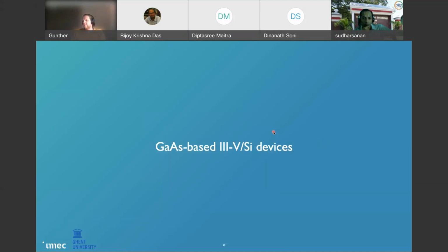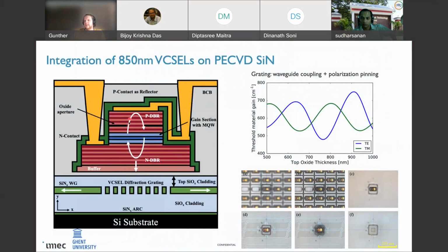So now let's have a look at gallium arsenide-based devices. I already showed you this picture of the VCSEL, so a gallium arsenide 850 nanometer VCSEL that was transfer printed on top of a silicon nitride waveguide circuit. In this case, it's PECVD silicon nitride, where we use the grating to couple light into the silicon nitride, but actually we also use it as a way to pin the polarization of the VCSEL. This is a one-dimensional grating, which will have a different reflection coefficient for TE and TM polarized light. And by optimizing that, by choosing the proper spacing between the VCSEL and the silicon nitride, we can create a substantial difference in threshold gain for TE and TM polarized light, and hence pin the polarization of the device.